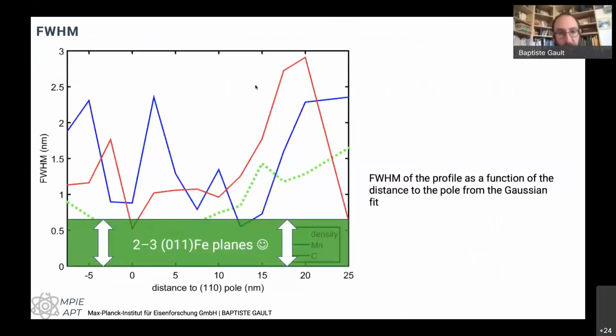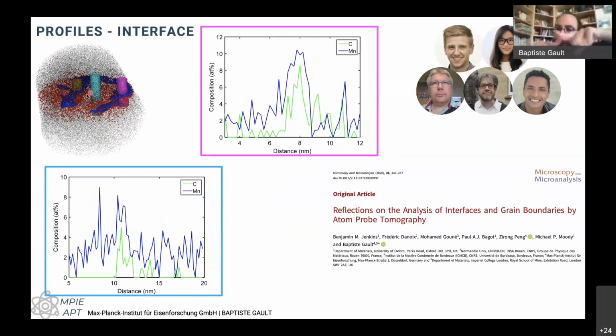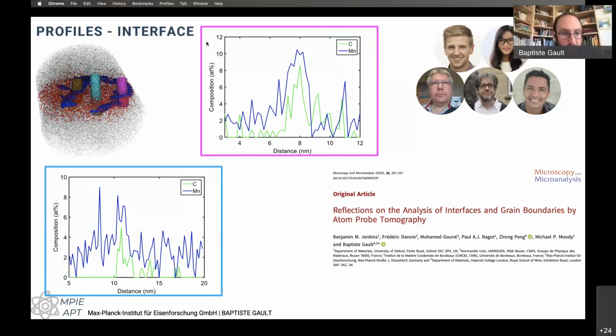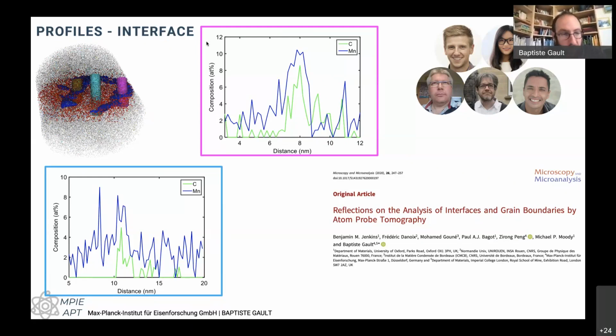For example, if I get back to this, here are dislocations accommodating the misorientation between the two grains, right? You can see that the segregation of manganese carbon would be about a nanometer or 2, maybe max, around this. This one that is slightly less segregated would have a profile that is slightly thinner. What we also see is that it's really not homogeneous all along. The dislocation tends to have broader regions, and this might be due to kinks that we just can't resolve. But there's really pretty work that was done. I can send you the link afterwards. Science Advances.